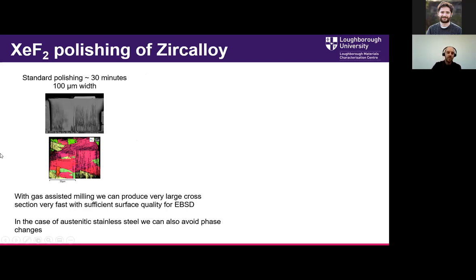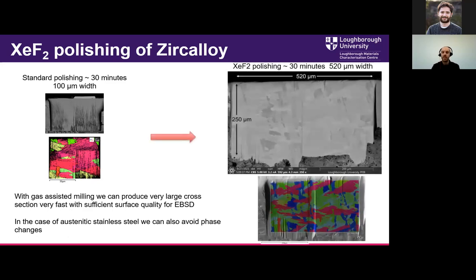So here's an example of a zirconium sample that was cut. We took around 30 minutes to make a 100 micron width cross section. And you can see it's got horrible curtaining on this side, and the EBSD looks pretty poor. You've got lines running through it, and also the grains have got sawtooth edges where you've got these curtaining effects.